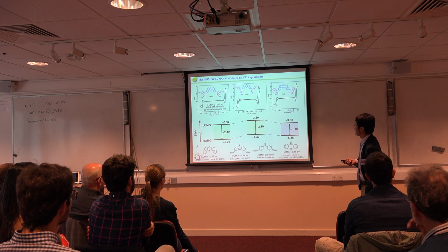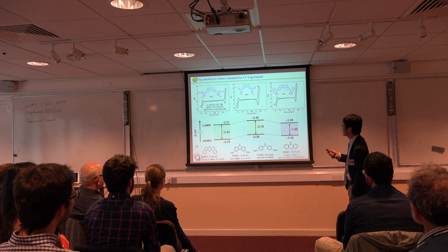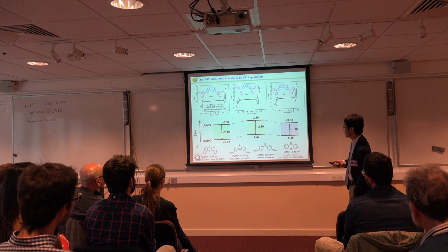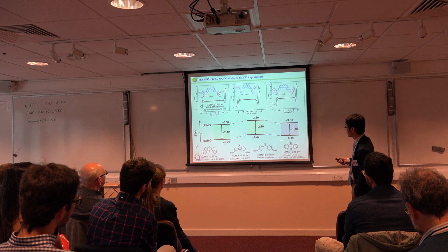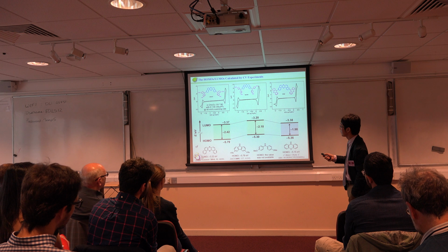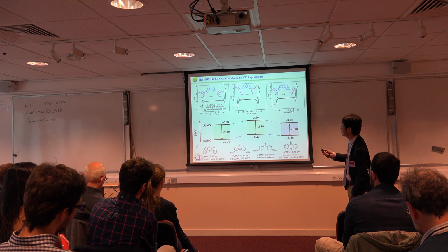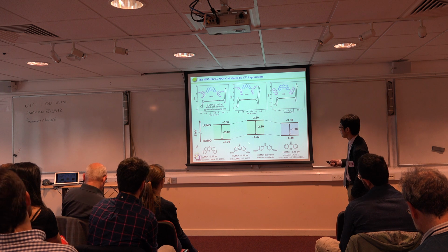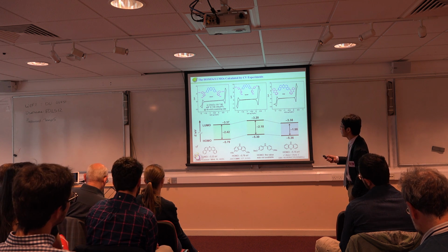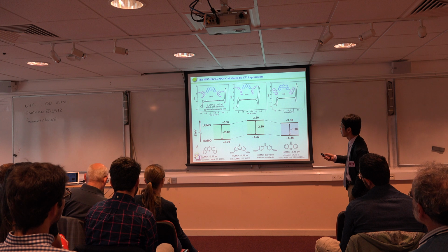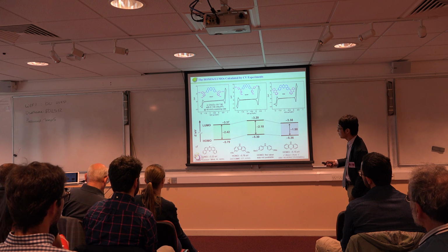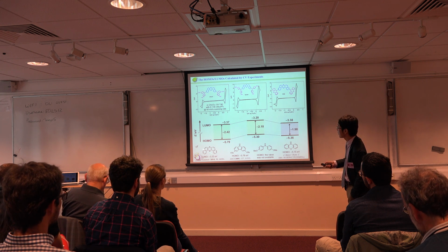Cyclic voltammetry experiments showed very nice reversible curves, as shown here. When compared to the acceptor unit and the donor itself, as you can see, the oxidation process affects the oxidation level of the donor, while the electron accepting process affects the electron accepting level of the acceptor.